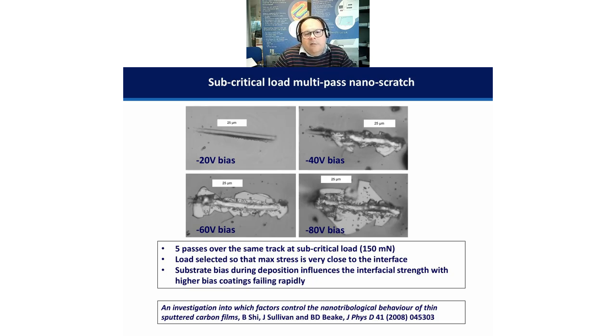So here, in 5 repeat passes with the minus 20 volt bias applied to the substrate, we get a little bit of edge cracking, but we can't see any exposed substrate. But as that applied bias increases, what we see is larger and larger interfacial failure between the coating and the substrate, incrementally extending to incrementally larger distances away from the scratch track itself. That's something which you would certainly not be able to predict from indentation alone. And it's not something, I think, which would show through in any kind of traditional tribological test that you might choose to perform on these samples.